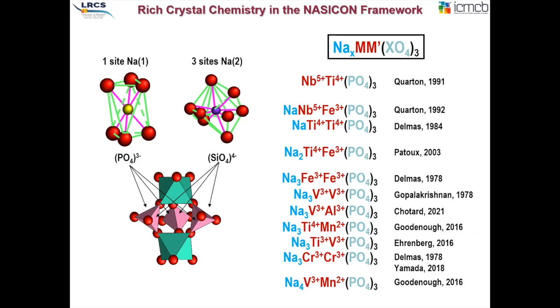So what I really enjoy, what you have to figure out about the Nasicon structure is that this allows for extensive chemical substitution. We can put basically whatever we want on the octahedral sites here with many, many different transition metals from iron to vanadium, titanium, niobium, manganese, chromium. And then depending on the oxidation state of these elements and depending also on the anion, here I mentioned only formulas with PO4, but PO4 can also be SO4, can be SiO4. So then depending on these numbers, we can adjust the number of sodium ions into the cathodes.